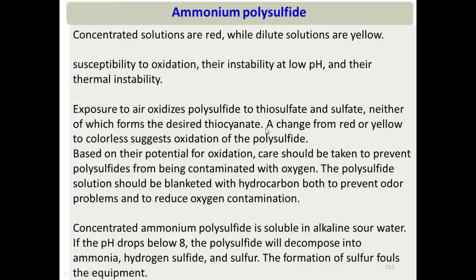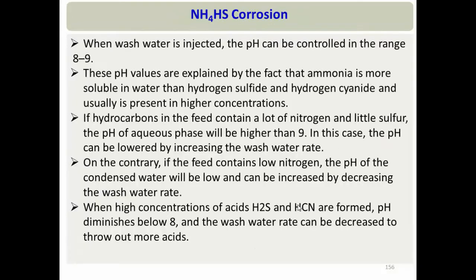That is the problem. It can be recognized because, with this oxidation, they turn from red or yellow to colorless, which suggests that the ammonium polysulfide has been oxidized. So we should avoid this oxidation, and because of that, polysulfide is generally blanketed with hydrocarbon to prevent odor or oxygen contamination. So that was all about ammonium polysulfide.